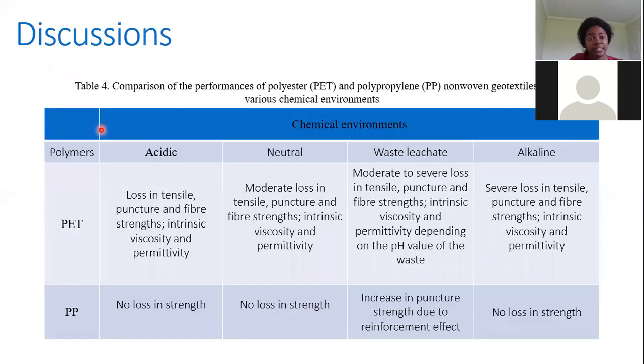So this table showed a comparison of the strength loss for the polymers, polypropylene and polyester, when they were subjected to various chemical environments. We can see that the most severe loss of strength occurred in alkaline environments for polyester. But then polyesters can be used in acidic or neutral environments, but one should be mindful of this. While polypropylene shows no strength loss, rather there was an increase in puncture strength in the waste leachate environment.